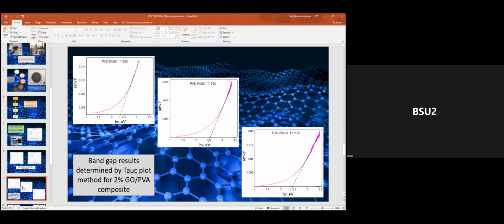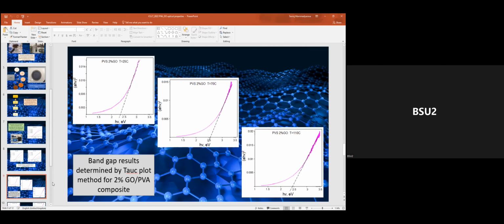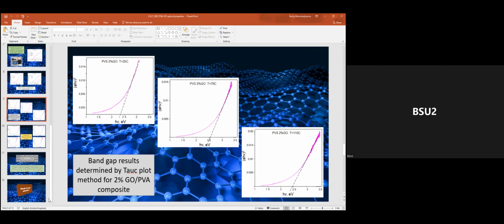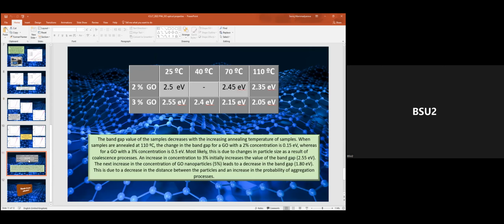According to Tauc, graphs were plotted and the temperature and concentration dependence of the band gap was determined. The band gap value of the samples decreases with the increasing annealing temperature of samples. When samples are annealed at 110 degrees Celsius, the change in the band gap for a graphene oxide with a 2% concentration is 0.15 electron volt.